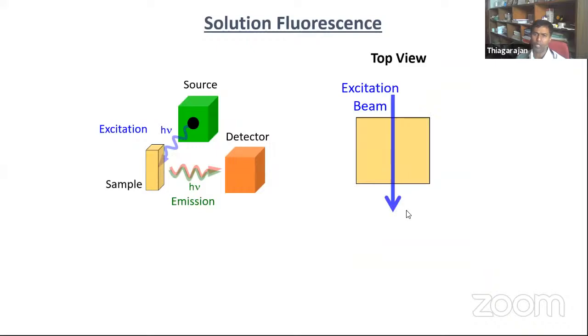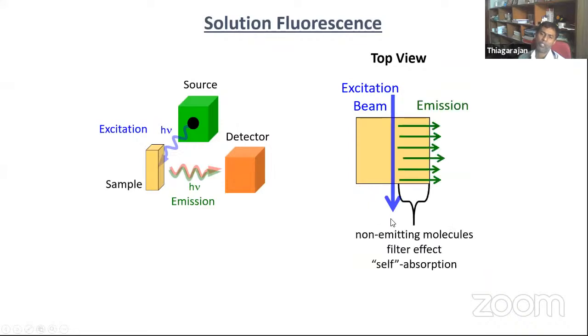When we record the solution, the wavelength of the light is passed through the sample and we measure the emission. Always we measure it in the perpendicular direction. When we record, what are the things we have to take care of? When we use a solution sample, we have to take care of the concentration. We should not use a very high concentration.